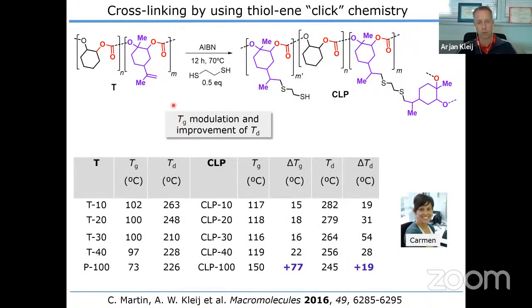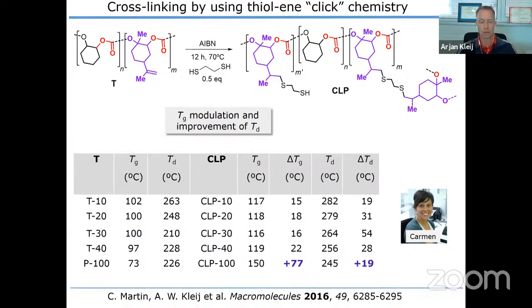As I said, you can cross-link these double bonds by thiol-ene chemistry. This is standard chemistry, making use of a radical initiator so that you can do thiol addition onto that double bond. If you then interconnect two polymer chains, you make the whole structure more rigid. And if you do that multiple times, you get a very rigid structure. In one particular case, P100, where we have 100% limonene incorporation, that means in every repeat unit we have a double bond, we can then get an increase in glass transition temperature of about 77, roughly 80 degrees. That is actually quite nice. It basically demonstrates the principle of curing or post-functionalizing these polymers.